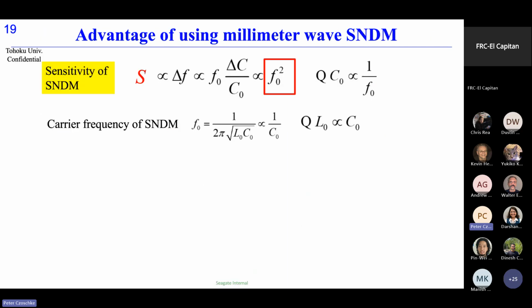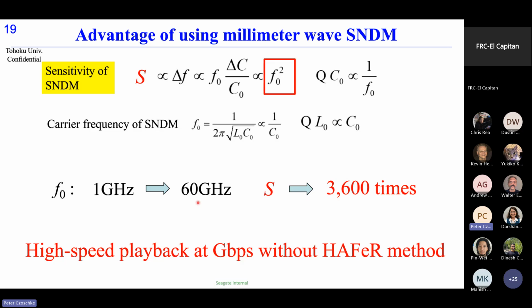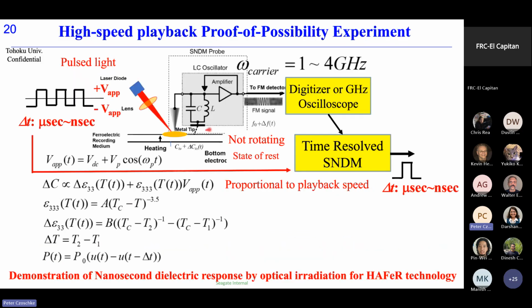But now, it is not impossible. And moreover, if we increase the oscillating frequency, some advantage is expected. The sensitivity of SNDM is proportional to the square of the oscillating frequency of the probe. Now we use a 1 gigahertz probe. And if we increase the frequency to 60 gigahertz, 3,600 times larger sensitivity can be expected. So a high speed probe at Gbps may be possible even if we don't introduce the HAFeR technique. But anyway, it is not impossible.